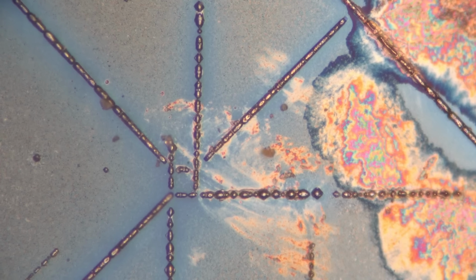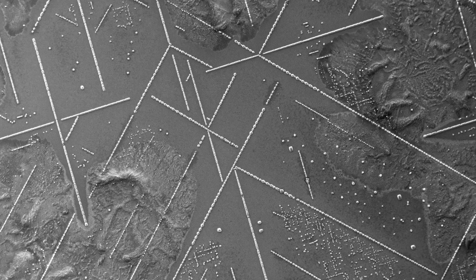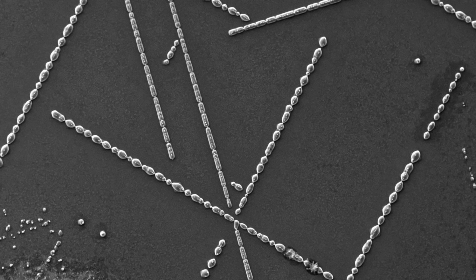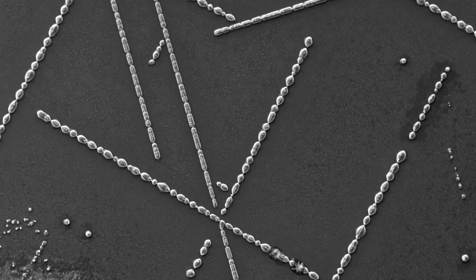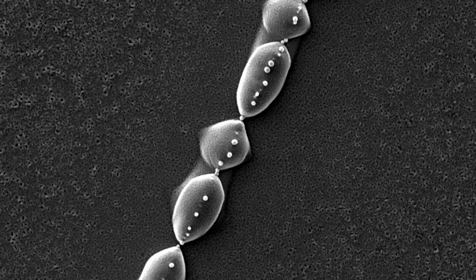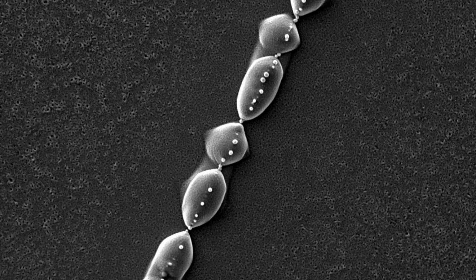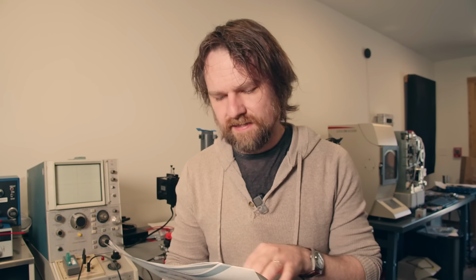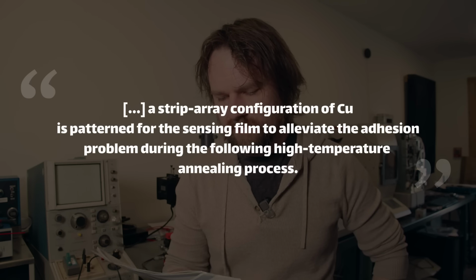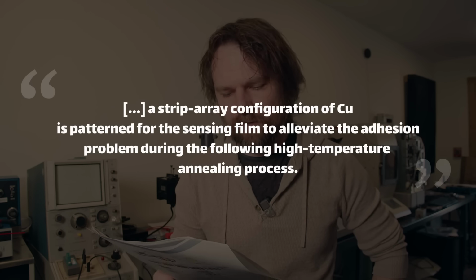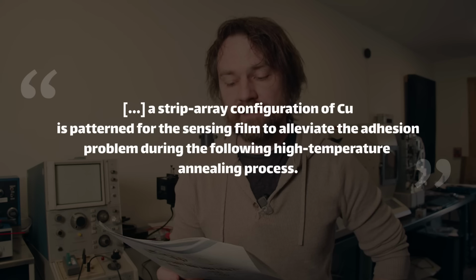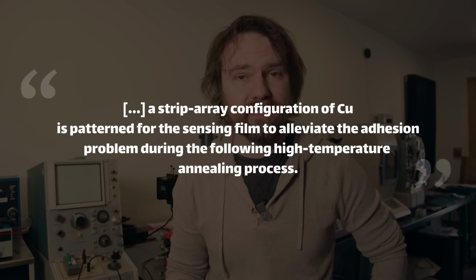As an aside, I think these geometric patterns are due to the copper oxide following the underlying crystal orientation of the silicon, which is, not gonna lie, pretty cool, but it's also not at all usable. So we have to rerun the experiment, but keep a better eye on temperature and try to err on the side of cooler. So I completely forgot to mention the adhesion problems that I ran into. The original paper makes a note of this in the methods. It says, quote, "A strip array configuration of copper is patterned for the sensing film to alleviate the adhesion problem during the following high temperature annealing process."